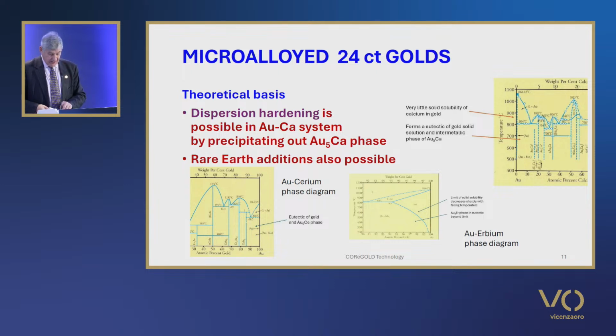reference to the phase diagram shows that there's virtually no solid solution of calcium in gold and that there is a eutectic comprising 2 phases, gold and an intermetallic compound, gold 5 calcium, which has a high gold content. If this phase is finely dispersed in the microstructure, then we have the basis of a possible alloy system that could provide improved properties through dispersion hardening.